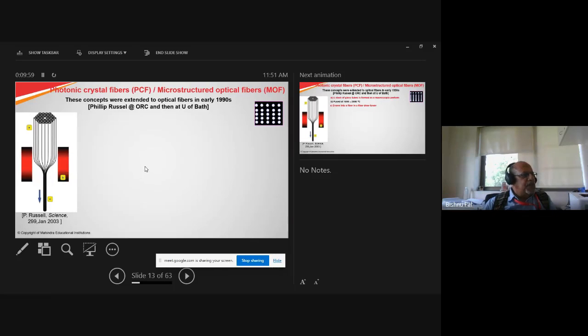So these are photonic crystal fibers, the equivalent of this photonic crystal structure, created by having a stack of glass capillary tubes, which are put within an oven that provides very symmetric, cylindrical heating. The whole thing collapses in a very uniform manner without creating any distortion in the overall structure, and that creates a microstructured optical fiber.